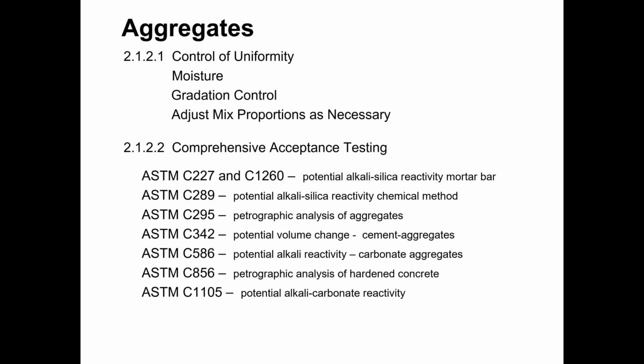All right, so a number of tests that can be used for evaluating our aggregates and their suitability for use in concrete. The petrographic analysis of aggregates, ASTM C295, is a common requirement that PCI has in place for architectural aggregates. Pretty much any architectural aggregate should have a petrographic analysis completed. If that analysis indicates that there are potential issues, then additional testing may be required.